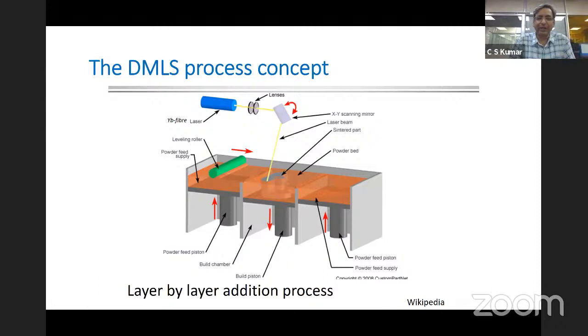Basically, we do layer by layer addition, wherein at one end you have powder, which is passed on to a build chamber through a recoater. The recoater puts the powder on a bed, and there's a laser beam, which is typically very small, with a diameter of about 80 to 100 micron, and it may have a power ranging from 200 to 400 or even 1000 watt lasers. When you apply it on a very small area, the energy density is so high that it melts the powder, and then when you switch it off, it very rapidly cools and binds to the substrate and makes a solid part on the previous layer.